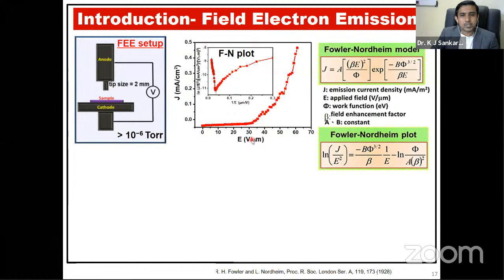To know accurately where the threshold voltage occurs, there is another form of the Fowler-Nordheim model, that is the Fowler-Nordheim plot. So this is the FN plot, which is derived from the current density versus the applied field. From this FN plot, the intersection of the high field segment and the low field segment provides you the threshold voltage, which we also call the turn-on field. The turn-on field means that at a particular voltage, the electron starts emitting.